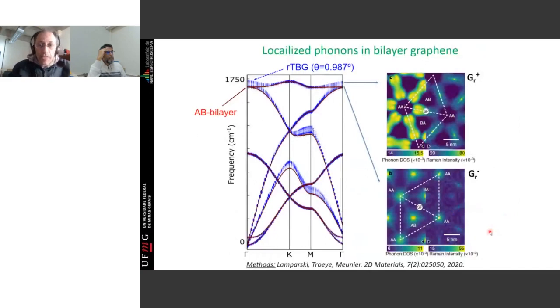Okay. Going further, if I now look into the main Raman peak, that's carbon-carbon stretching, if you have the AB stacked bilayer, you have a very specific frequency here. But when you have these superstructures, what you generate is a lot of modes that are activated. And what the theoreticians predict, where the theory here is tight binding, but a tight binding with thousands of atoms and overlapping integrals and so on to account for the supercell, to be able to describe these localized states, is that the phonons at higher frequency are localized at the strain solitons. And the phonons at lower frequencies are localized at the AA points, okay?